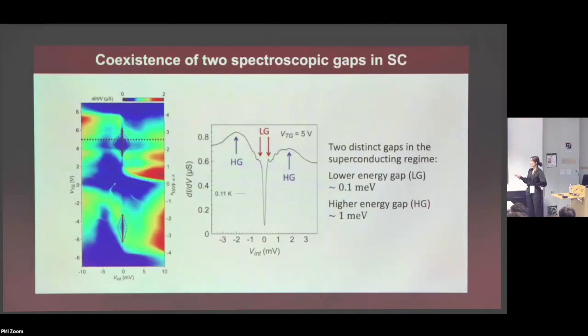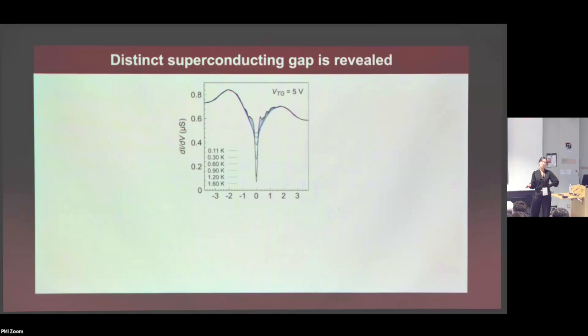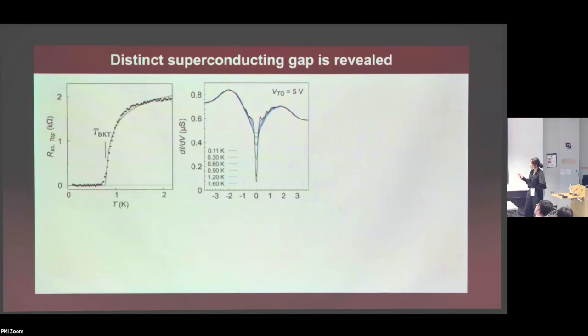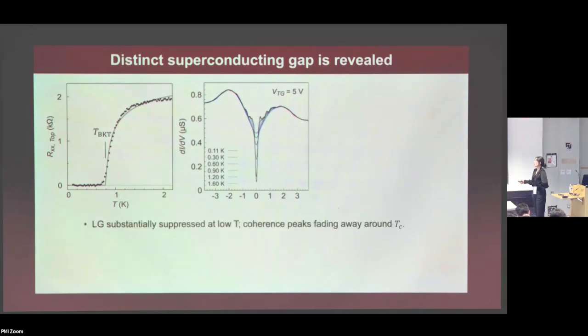Now we want to investigate what's going on here. And we can do that first by trying to increase the temperature and see what happens. So here's that same curve ranging from 110 millikelvin up to 1.6 Kelvin. You can see that, first of all, the zero bias conductance gets immediately lifted. And these little conductance coherence peaks in the low energy scale are gone around 1 Kelvin. But these broader shoulders, these high energy gap features, are still remaining. And now we can also take advantage of the simultaneous transport measurements as a function of temperature, and we can obtain that TC is around 1 Kelvin. And that's actually exactly where these low energy gap features are gone.